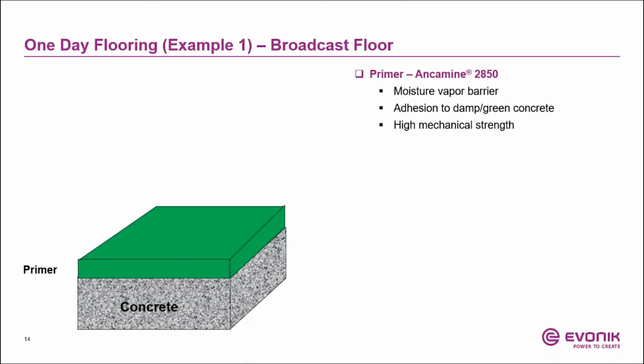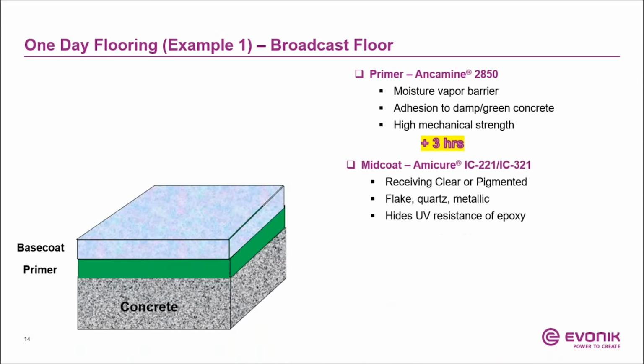The first layer that you put down on concrete is a primer. In this case, we recommend Ancamine 2850. Again, as I mentioned before, it's a low perm moisture vapor barrier. It has very good adhesion to damp concrete, very high mechanical strength. 2850 is a fast cure moisture vapor barrier. After 3 hours, you can apply the base coat.